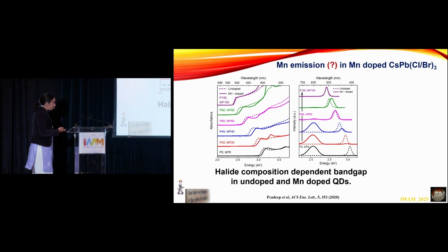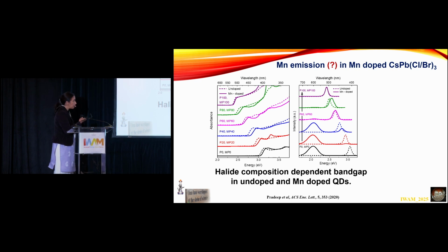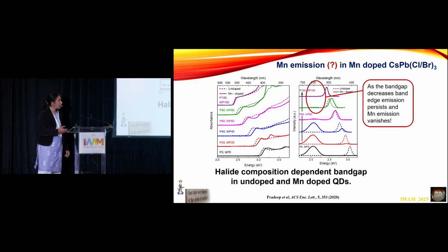So the first thing that people observed is this 2.1 eV peak, which has been attributed to the d-d transition of the transition metal ion. It has been used as a signature for the efficient incorporation of the manganese. And the absence of this peak in these cesium lead bromide structures, so the lack of manganese emission, is actually what was initially anomalous.